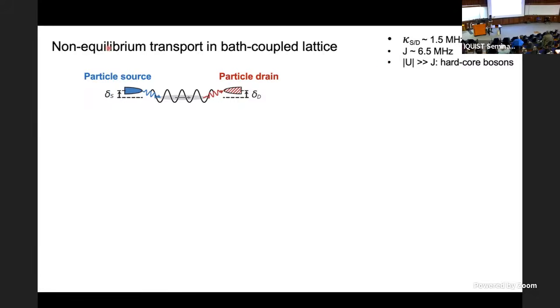Here is where I probably should point out the numbers. So kappa, if you remember, is the bandwidth of these particle source and drain. Okay, these are narrow band particle sources and drains instead of your typical chemical potential that you think of in a fermionic system. So that line width is about 1.5 megahertz. The tunneling in the lattice is about 6 megahertz. And for this particular set of experiments, we're going to stay in the so-called hardcore boson limit because our interaction is so much larger. So think of it in the case where you can have at most one particle per site, okay, just for this particular experiment.